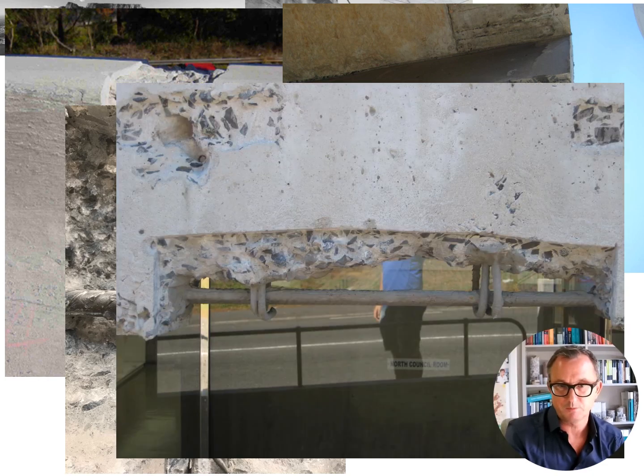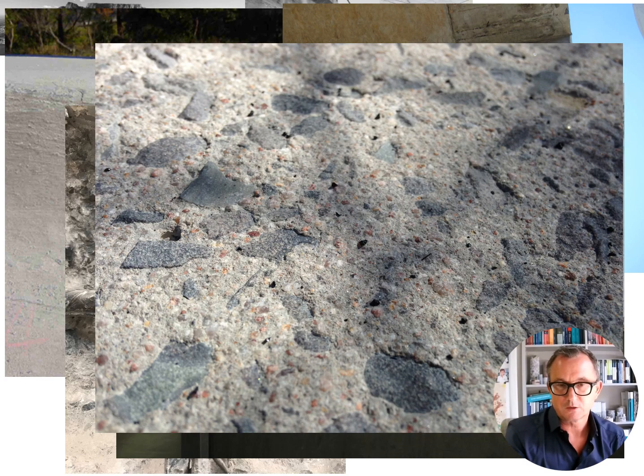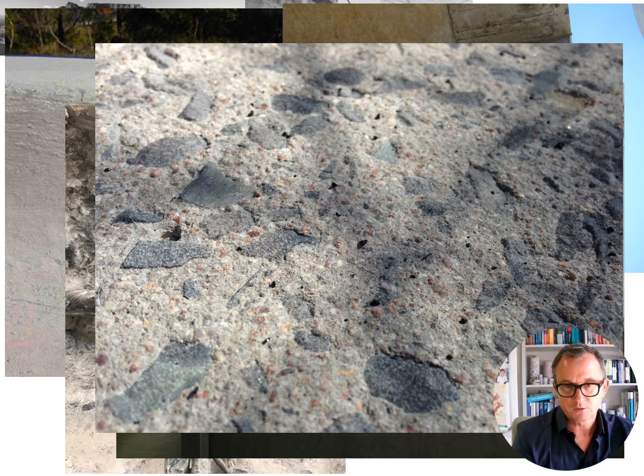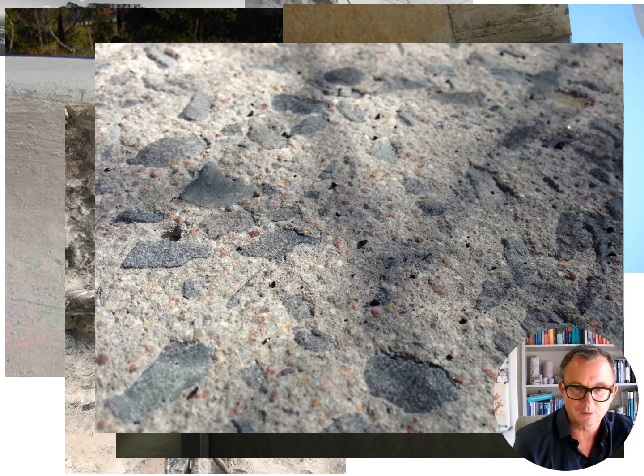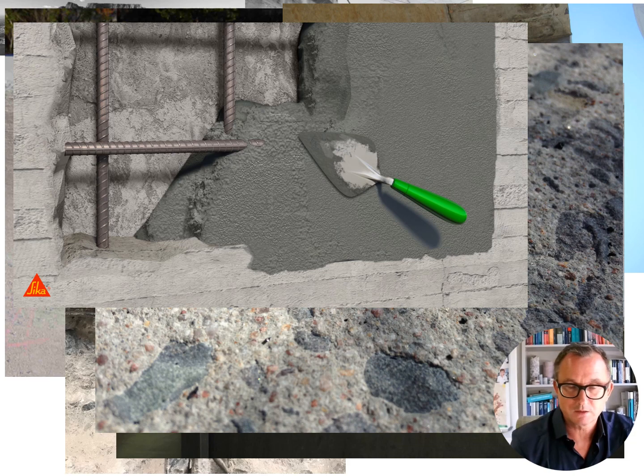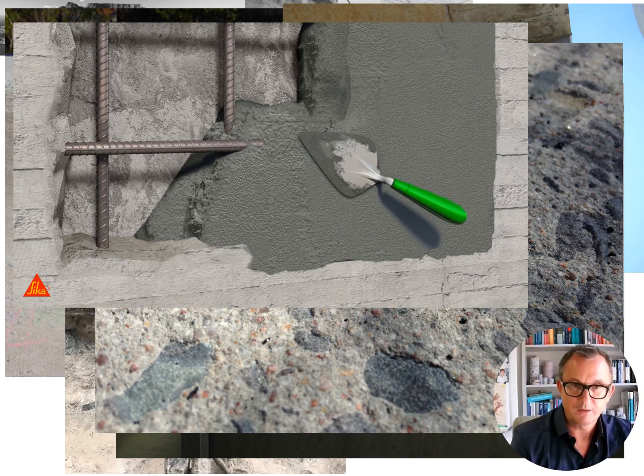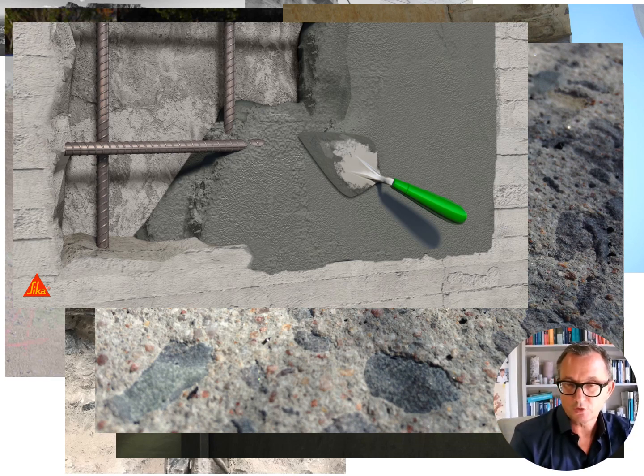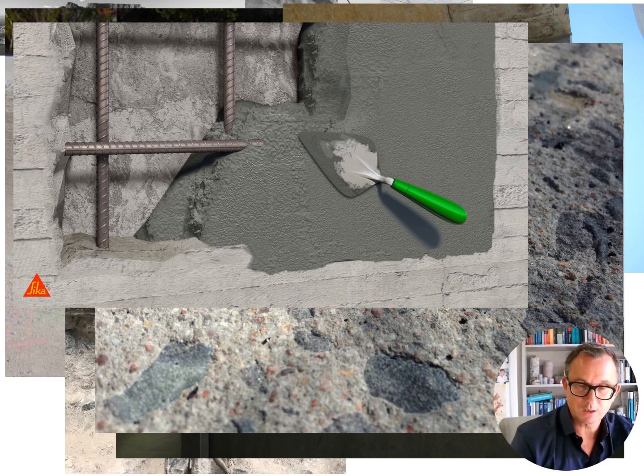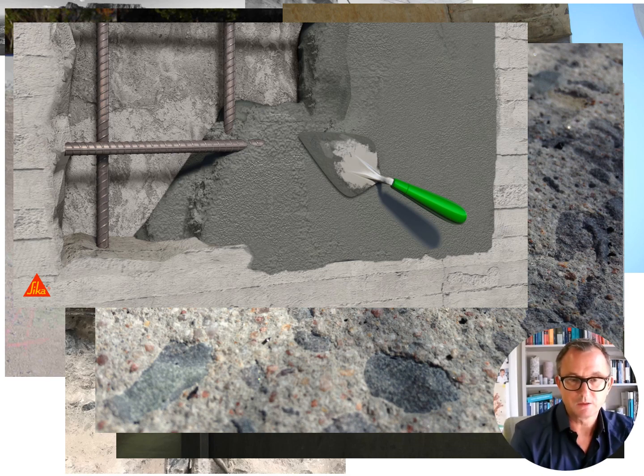In terms of concrete surface preparation, one does not need to provide a very rough surface. Typically a surface roughness of around two, three or four millimeters is sufficient to give good bond between the substrate and the repair mortar. Once the substrate is prepared accordingly, you can apply the patch repair mortar — often a proprietary repair mortar from industry suppliers, though you can also mix your own. It needs to be cured, and following curing these mortars often receive a surface coating to provide further protection, curing, and aesthetic appeal.